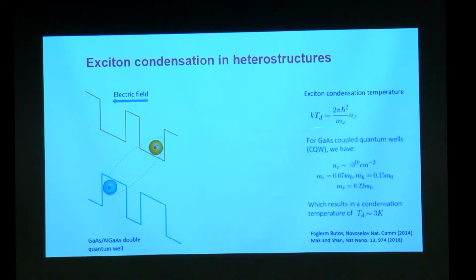It turns out that the number at which exciton condensation can occur is given by this. Because in standard gallium arsenide, aluminum gallium arsenide heterostructures this distance is about 15 nanometer, the typical number of excitons is approximately 10 to the 10 per square centimeter. Masses are like this. Eventually you plug this all in, and it will give you a rough condensation temperature of 3 Kelvin or so. Okay.